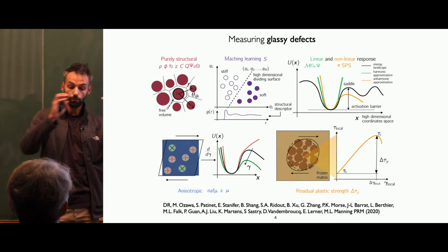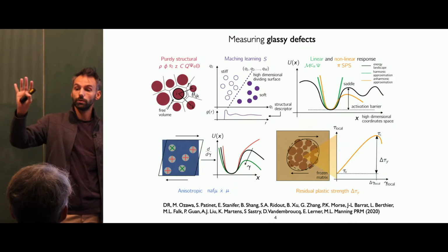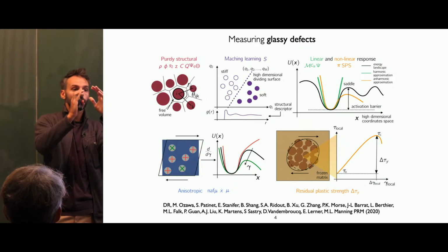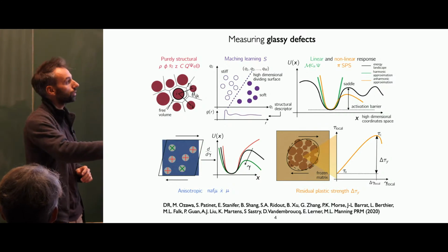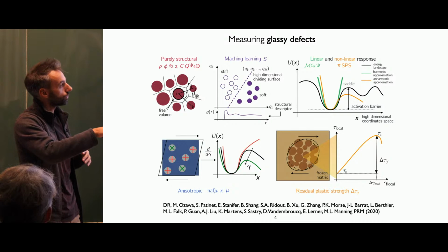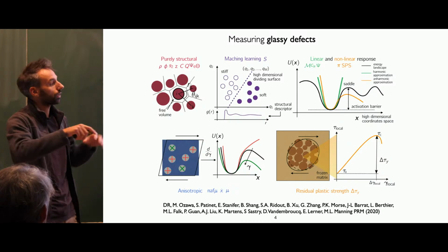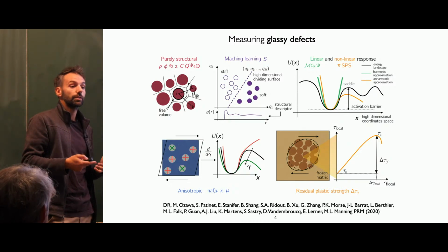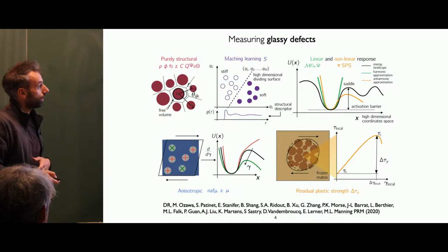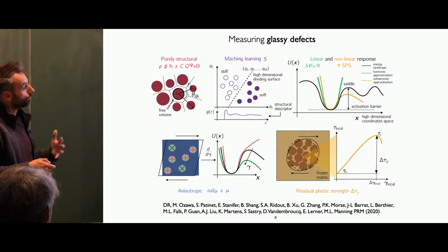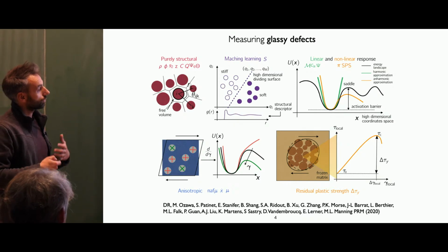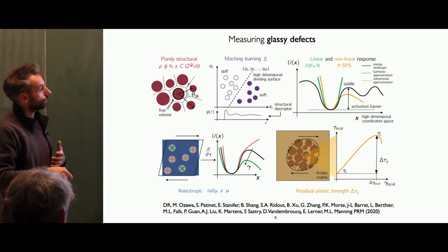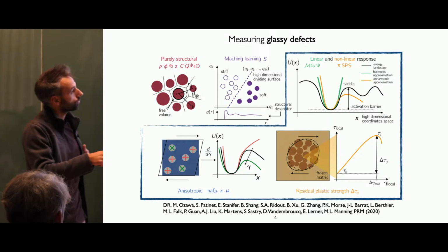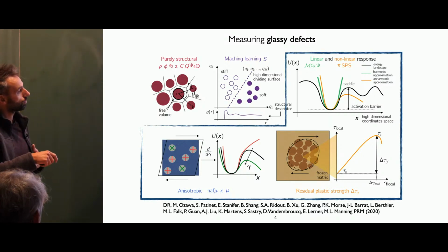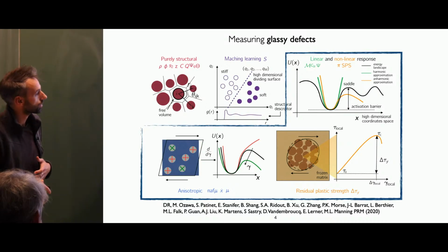Where you take a piece of glass, and in every part of the glass you shear it locally. So you freeze everything in the system, you take a cavity and you start to shear it in one direction. You do not monitor the global stress and deformation, but the local stress and the local deformation. And you are able to measure for every patch of particles how much stress I need to put in my system to see it yield. When you apply this kind of method to a glass, even if you don't deform it, what do you typically see? My talk will focus on energy landscape anisotropic indicators and local yield stress.